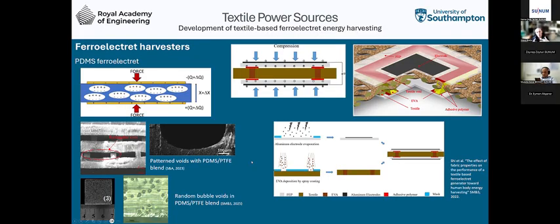So from a wearables point of view and from a textiles point of view, we want to work with very flexible, soft materials. Initially we did a lot of work on PDMS as the material for this, and we micro-engineered deliberate structures with precisely controlled voids. Then we can predict exactly how this material would behave. But PDMS isn't the greatest electret material. It doesn't store charge particularly well, particularly stably. So we added PTFE, which is a very good electret material. We added that in a powder form to the PDMS, and that improved the performance considerably.